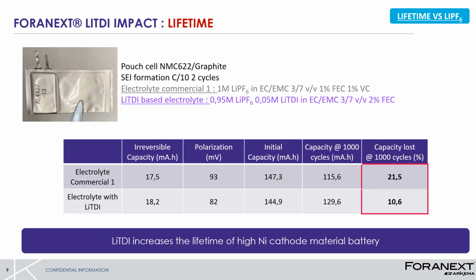Besides increasing the power performances, LiTDI as an additive enables to improve the battery lifetime. At pouch cell level for NMC622 graphite, we compare 2 electrolytes, a reference one and a LiTDI-based one. LiTDI allows to limit the capacity loss thanks to several roles in the electrolyte. Indeed, LiTDI plays an important role to stabilize the SEI on the graphite, the CEI on NMC, and also to stabilize LiPF6 due to its scavenging effect. Indeed, LiTDI is able to replace a lot of additives. Thanks to that, we are able to simplify a lot the electrolyte formulation.